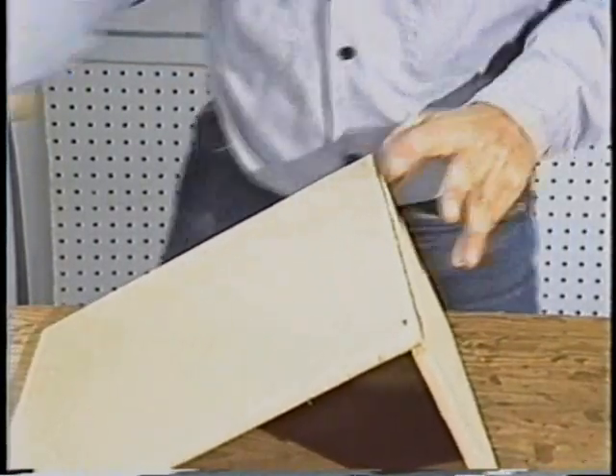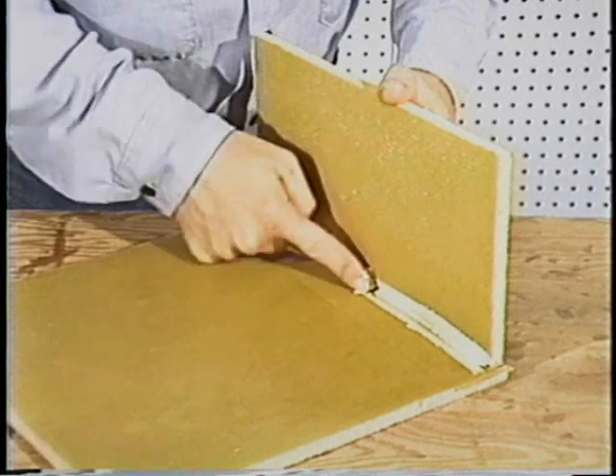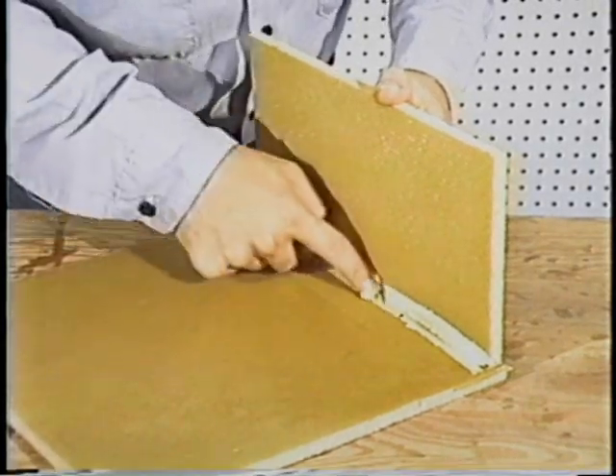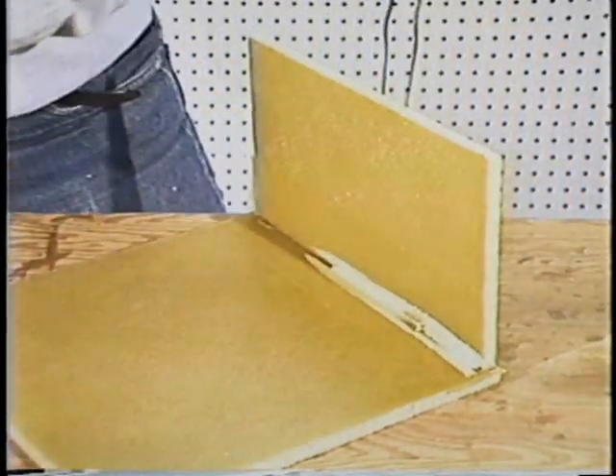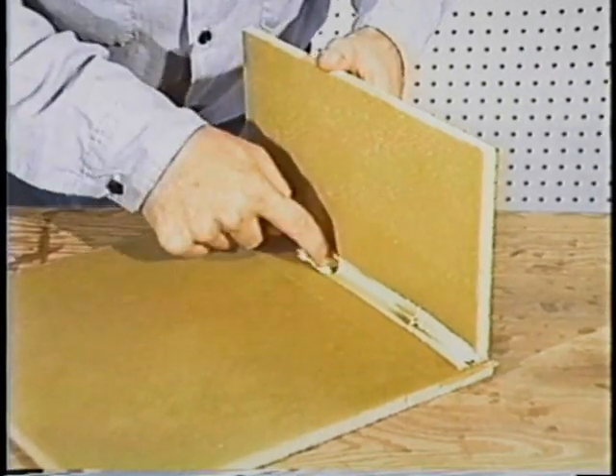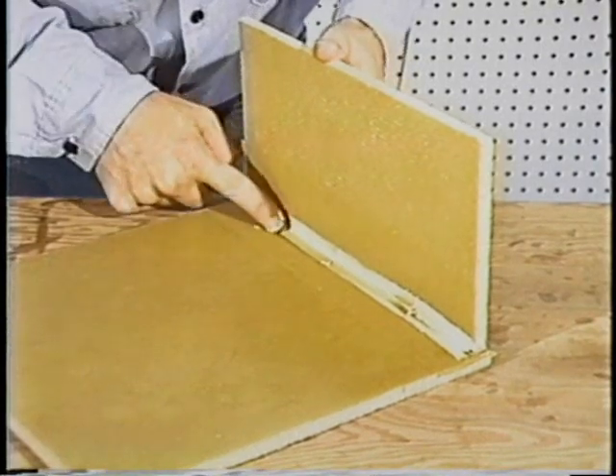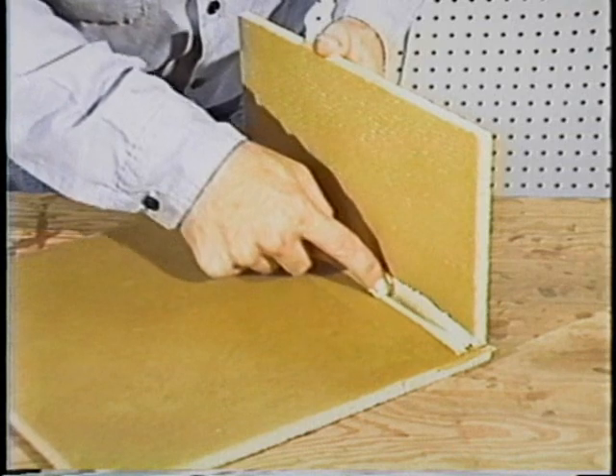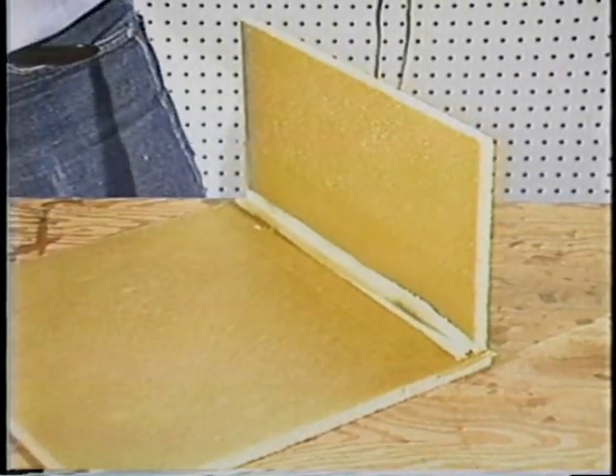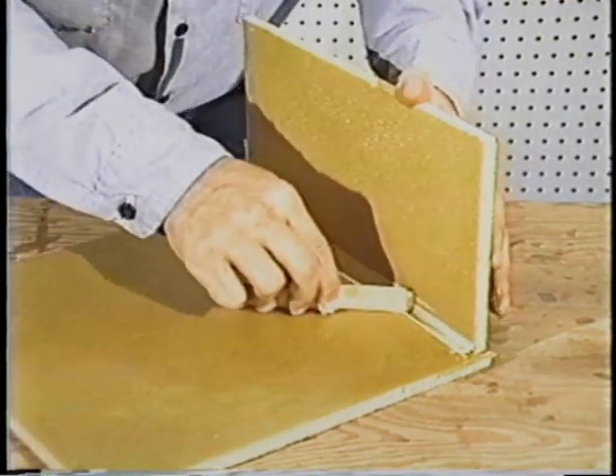Now we get on and we push a few nails. Now this part's pre-cured, so we're probably going to have to use a hammer to put these nails in. Now we can take the micro we've mixed up previously, dry micro, wipe on a bead of dry micro in the corner, wiped in with your finger to fill what would be an inevitable void there. You'd have an air bubble behind there and it would cause weakness. So we want to fill this with dry micro so that the glass fiber is supported as it goes around this corner. Gives you a good radius. We want to also scrape off all that excess.